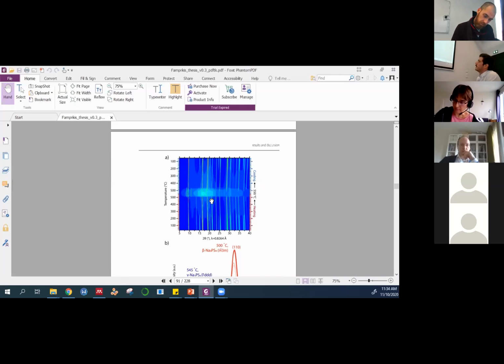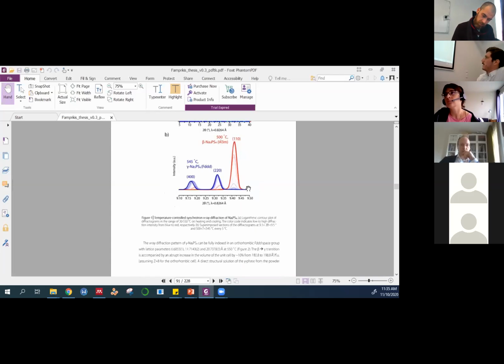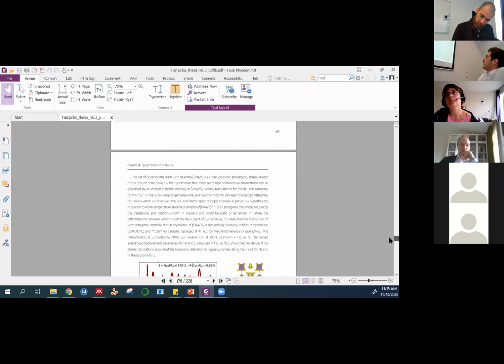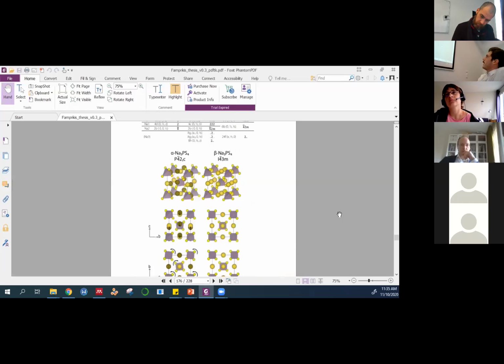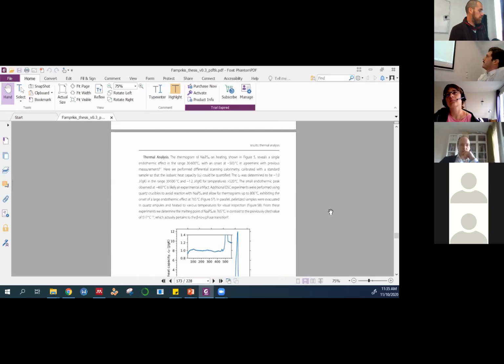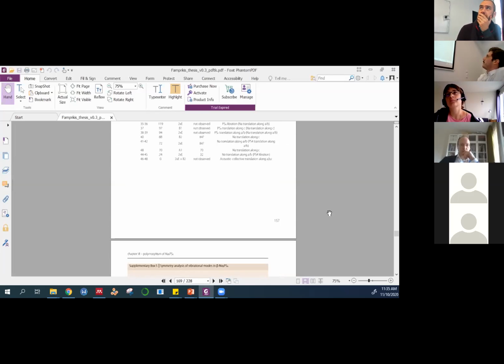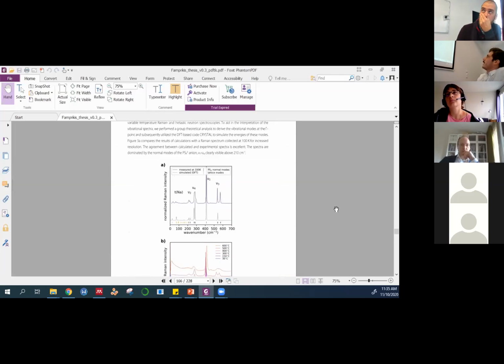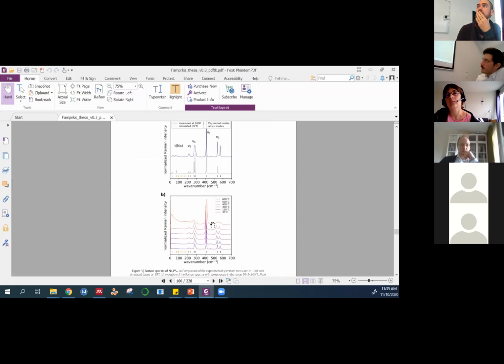Another point to make, and this is in the last chapter, is that even when we are in the gamma phase, we still see a very clear signature of a PS4 anion, which is charged 3 minus. So that's another way of saying that I need to have 3 sodium to coordinate that. I cannot really have a structure with PS4s but not 3 sodium around it, right? And it's zoom in. Yeah, I see.